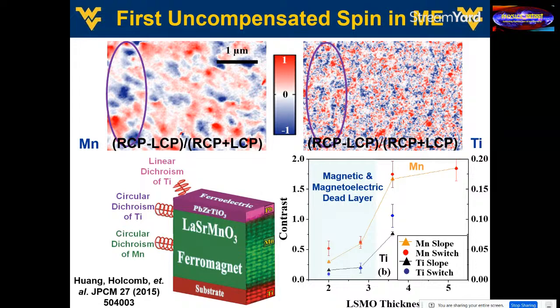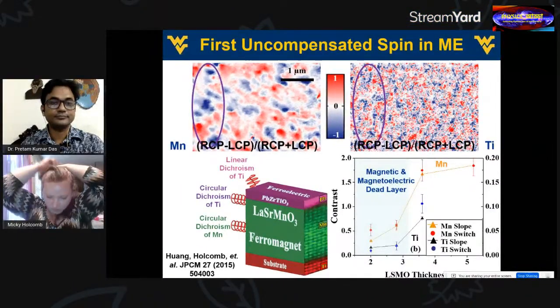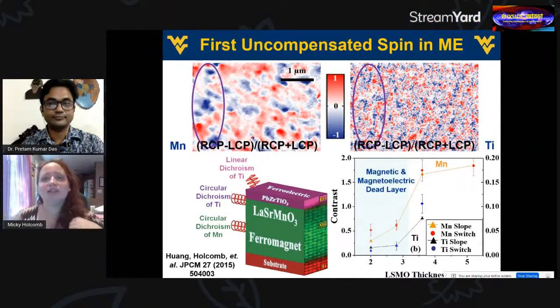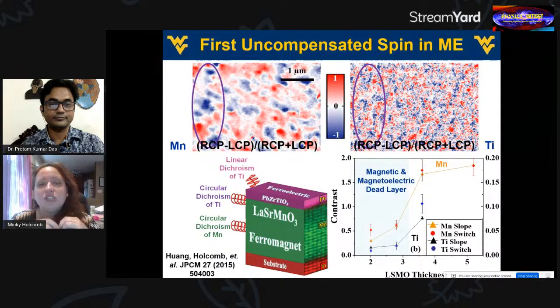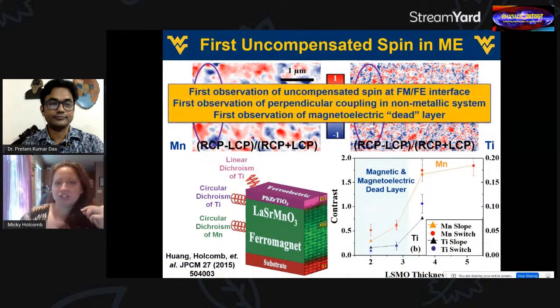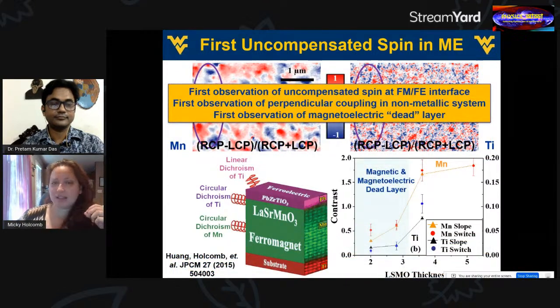People thought this coupling would exist, but they're like, okay, if this is an interface effect, we might be best having devices that have a lot of interfaces, meaning relatively thin films. But what this work was able to show is that there is a bit of a limit to that. So yes, it's great to have lots of interfaces, but if you make your magnetic material too thin, you will lose the effect entirely. So there is a bit of a limit on how low you can get this to go. So just a few quick, let me brag a little bit about this work.